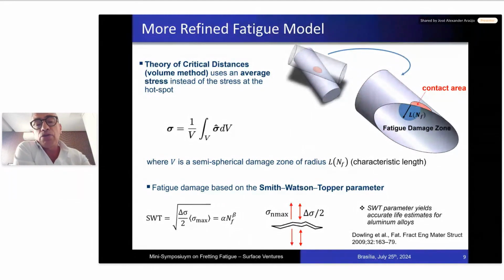We have considered and presented in many talks that fatigue is not a punctual problem, mainly when you have fatigue in the presence of stress gradients. You should not consider the fatigue problem as a single material point problem, but the fatigue problem should be considered within a process zone. The size of this process zone depends on the estimated life for this component. So you should compute these damage parameters as the Smith-Watson-Topper, not in a single material point, but within this process zone. This process zone gives you an average of the severity of the damage for this specific material.